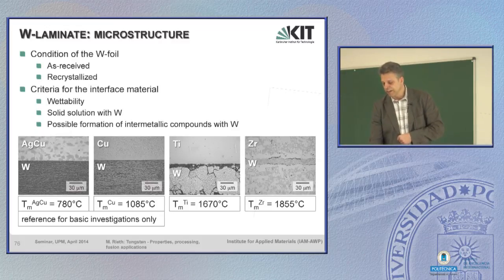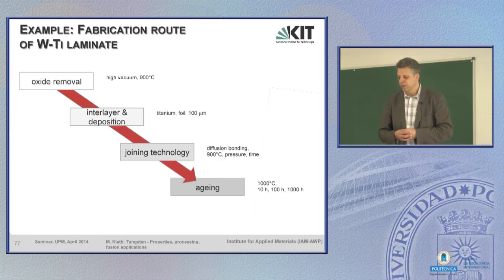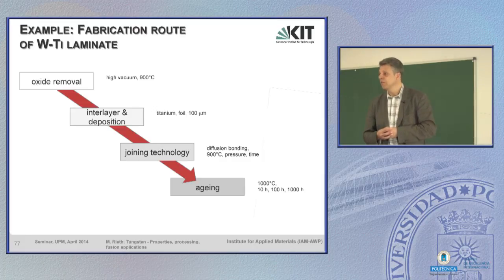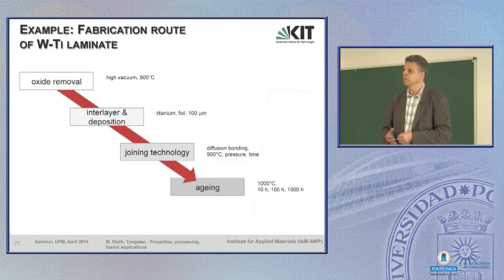We have tested several inner layers, copper, titanium, zirconium, with more or less good results. You can see it here. And in principle, the question was, can we make pipes out of such structures? Because this is the ultimate goal. We need cooling applications, how to do pipes. The typical fabrication route looks like this: in the first step, oxide removal from the surface of the tungsten, then layer deposition, then we join the whole thing together and perform some aging tests to see whether we can use the structures for a few years.